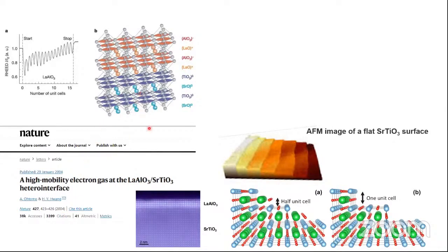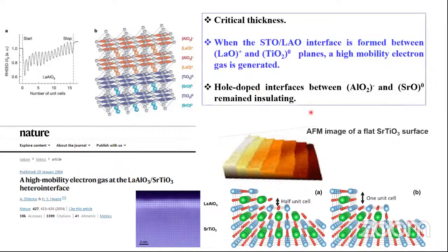And in this case, the films were made by pulsed laser deposition, and prior to pulsed laser deposition, the surface of the STO substrates is prepared in a controlled way, in which one can get titanium oxide terminated layers on the top or strontium oxide terminated layers on the top. It was seen that when the starting material had the titanium oxide terminated surface, the two-dimensional electron gas formed, which is conducting. And when the surface was strontium oxide terminated, the interface remained insulating.